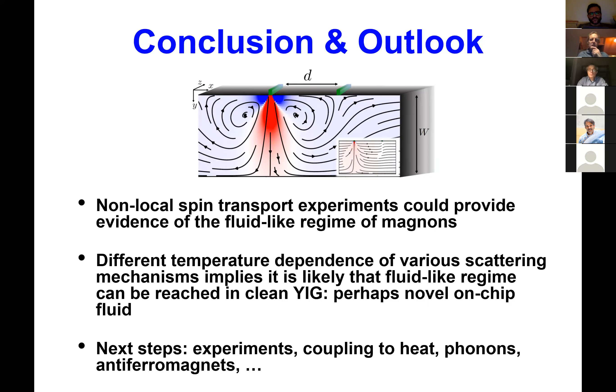There are basically two processes: you need spin non-conserving collisions to destroy spin, and you need to know how far magnons travel. The relative importance of magnon-magnon versus magnon-phonon scattering changes with temperature, and I don't have a good theory for this at the moment. Part of the reason is that YIG is experimentally excellent but its unit cell has around 80 atoms — it's actually a ferrimagnet — so it's not really a simple Heisenberg ferromagnet. The details are messy.